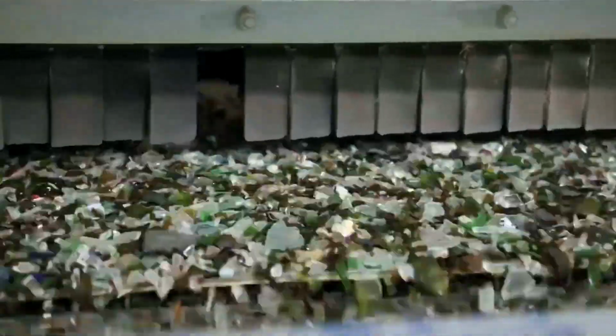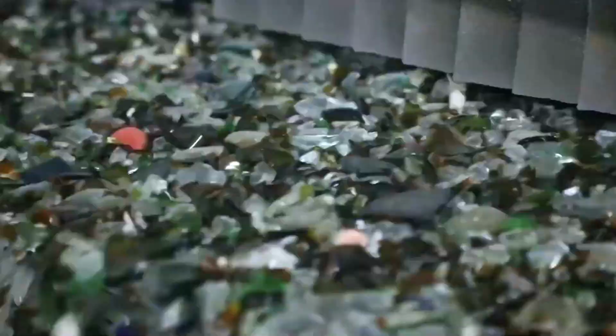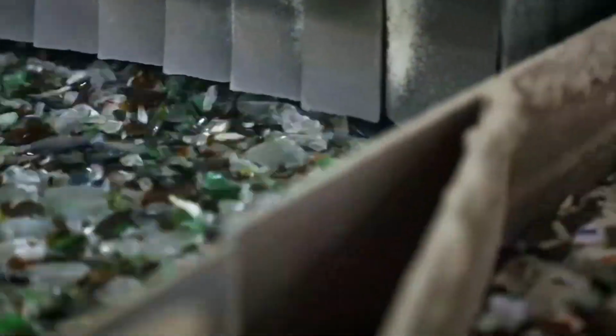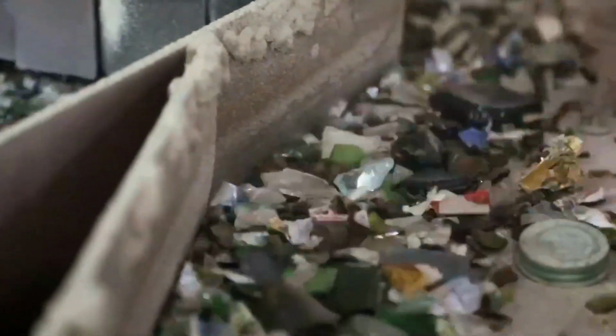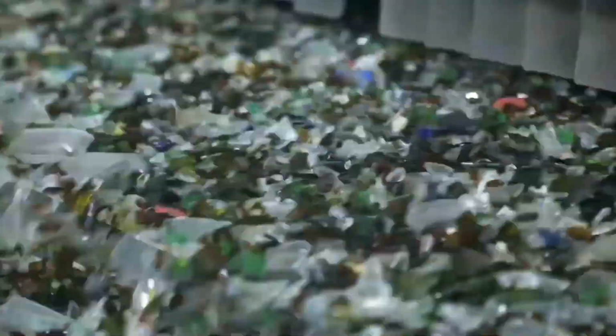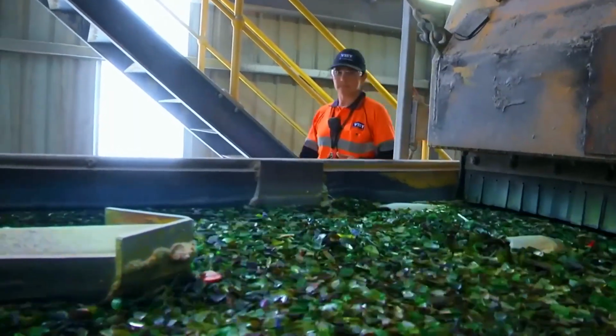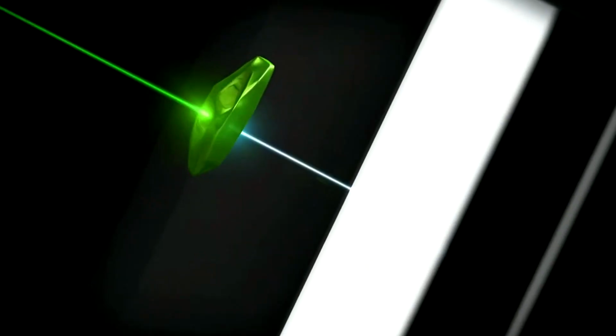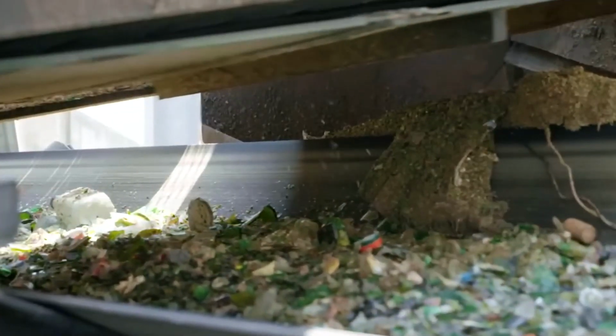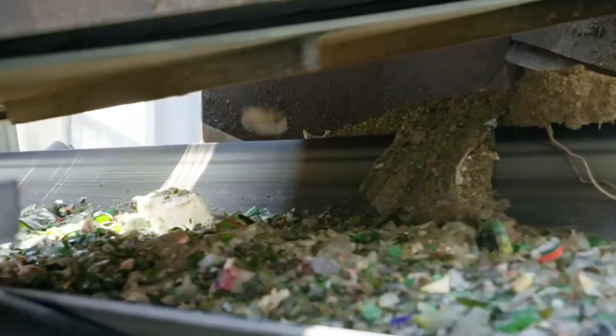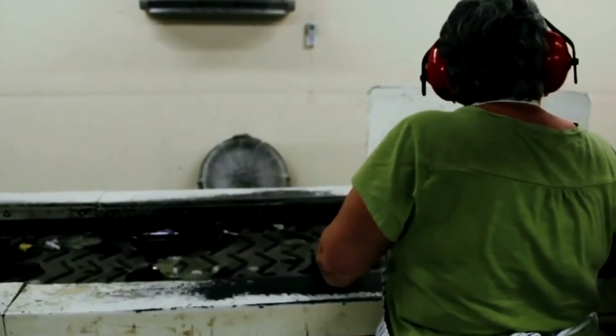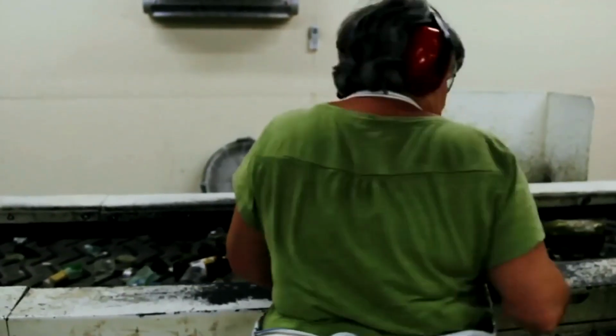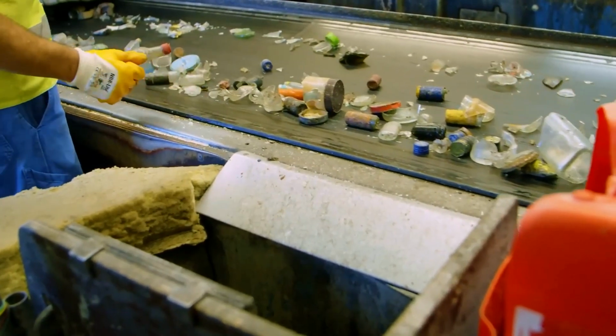Because it is broken down so small, cullet melts much faster in the furnace, saving up to 40% of the energy compared to using raw materials like sand or limestone. And this is not the limit. One can notice how the cullet enters a powerful suction system, where a strong stream of air strips away and blows off any leftover label fragments, leaving the glass even cleaner.